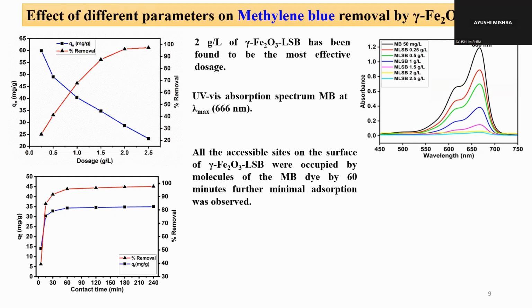To study the effect of contact time on the adsorption process, we performed the experiment with increasing contact time. We can clearly see that at 60 minutes we have the maximum percentage removal. After that, from 60 to 240 minutes, there is no such change, which may be due to all the active sites on the adsorbent surface being covered with methylene blue dye.